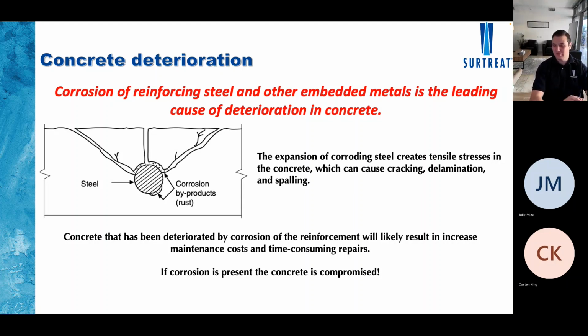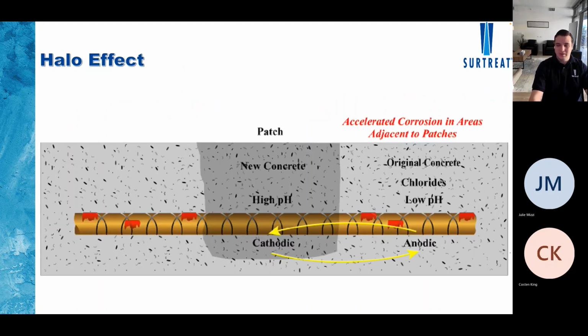Now, once that happens, it spreads throughout the rebar. And once concrete has been deteriorated by corrosion, it's going to be more time and more cost to repair. Now, it's important to know that if corrosion is present in concrete, the concrete is compromised. And to this point, the thing that we've been doing is just patching, right? We see a spot that's corroded, we see some spalling happening, and we just patch it, and we think it's repair. But this couldn't be farther from the truth.